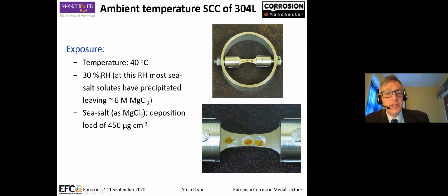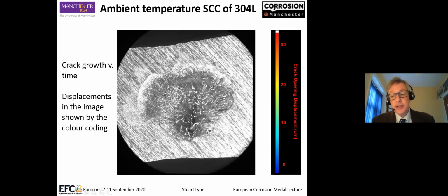So at 30% humidity, most of the sea salt solutes have precipitated. You're just left with about 6 molar magnesium chloride. So if anyone does experiments in boiling magnesium chloride, it's about the same molarity. So you can see these samples have cracked here. And what we wanted to do is see if we can image these cracks over time to get a crack growth rate, and then use fracture mechanics analysis of the sample to understand what the K1SCC fracture mechanics threshold for cracking was. I'll just run this animation.